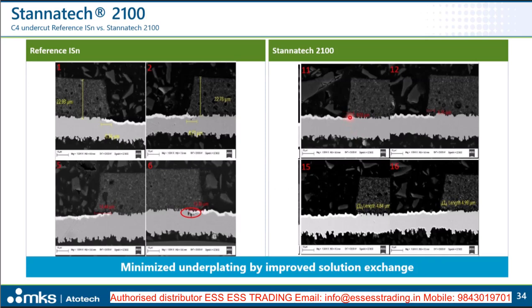We still see an undercut with the 2100, but it's, let's say, reduced by half. So we have an undercut of 4 to 5 micron versus really 10 micron in these areas. So it's reduced a lot, and we also don't observe this copper corrosion in these undercut areas. So it is also caused by the better solution exchange during the process.